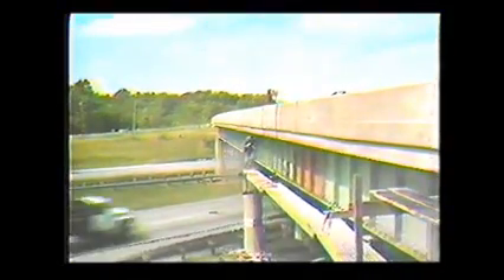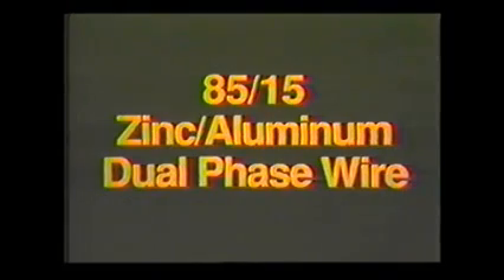Akron Sandblast and Metallizing Company's next project for the Ohio program is this 364-foot by 32-foot bridge which spans Interstate 71. Preparation of the surface was the same as that used on the first bridge, but that's where the similarity ends. This time, the wire being fed into the metallizing gun is an alloy of 85% zinc and 15% aluminum. The 8515 material is a dual-phase alloy combining the best characteristics of both zinc and aluminum. The zinc-rich phase sacrifices itself to protect the more noble steel. The aluminum-rich phase, meanwhile, acts as a passive barrier against harsh corrosive environments.